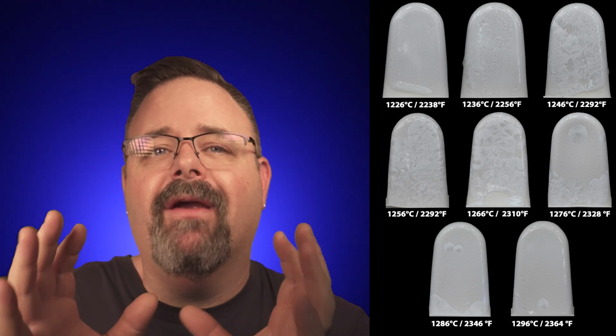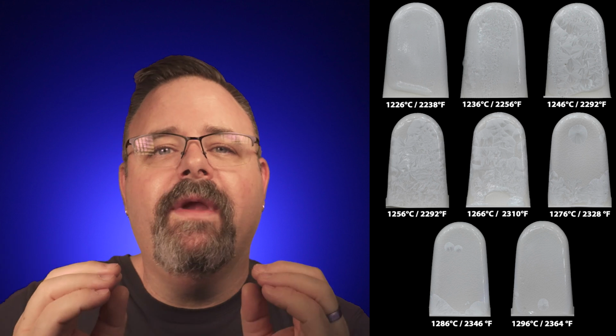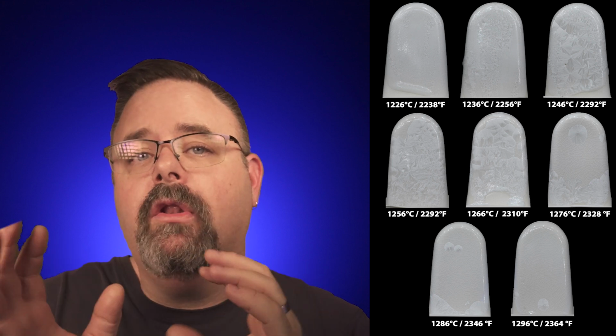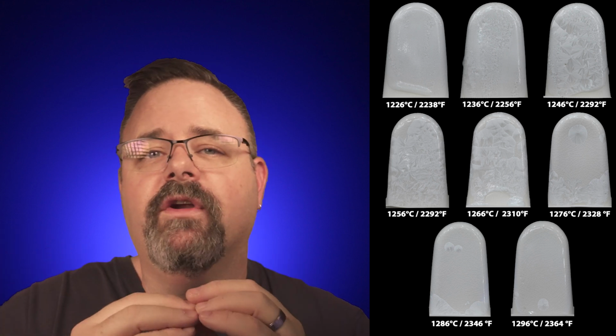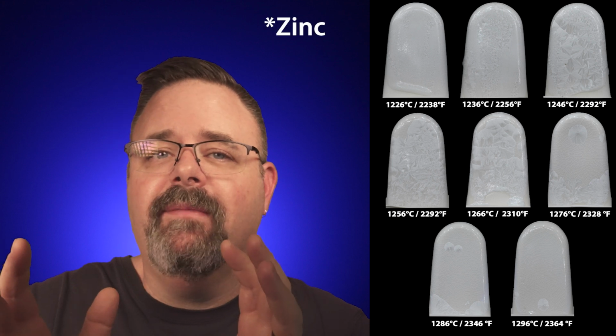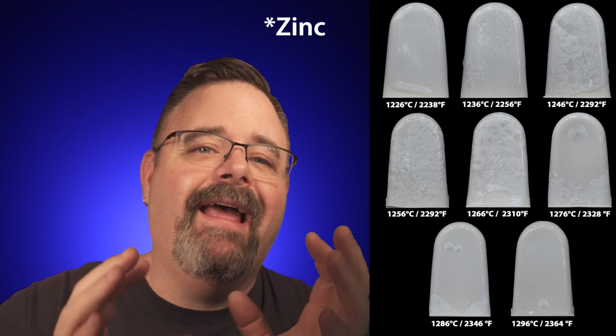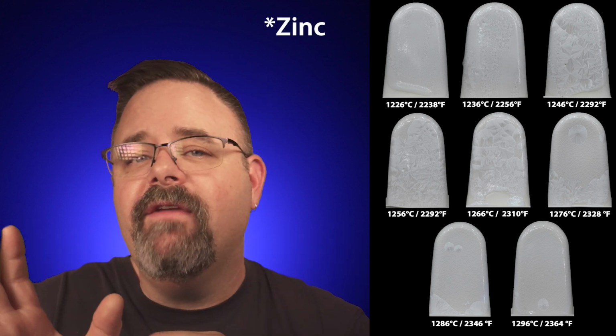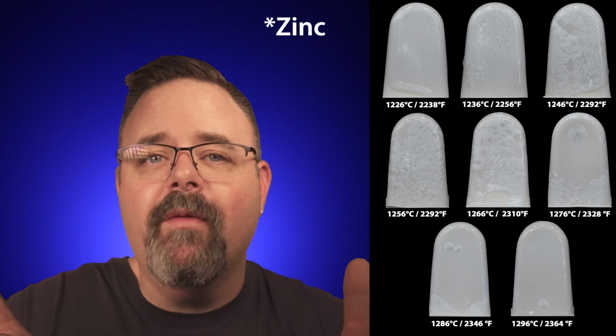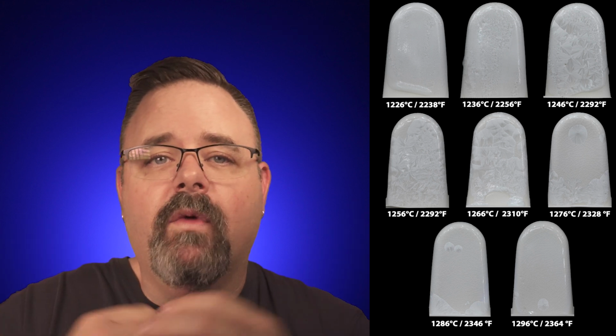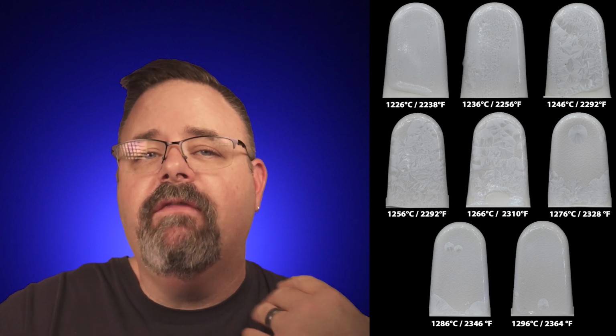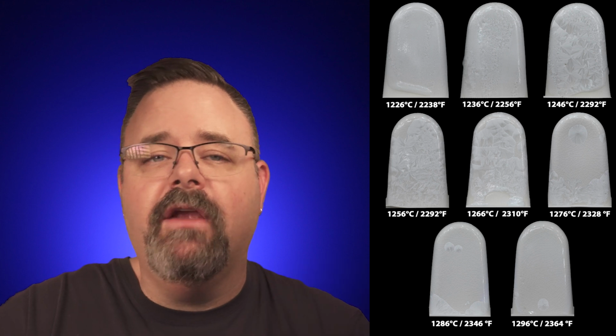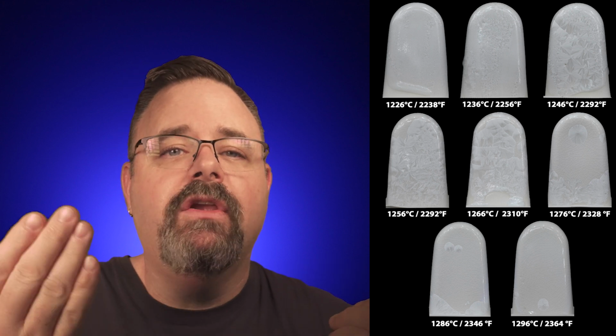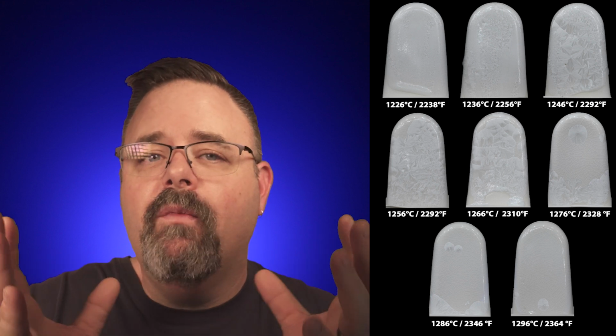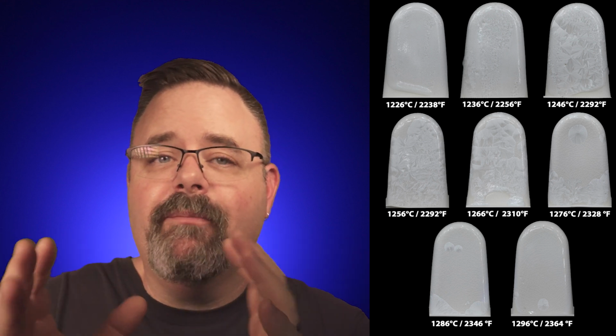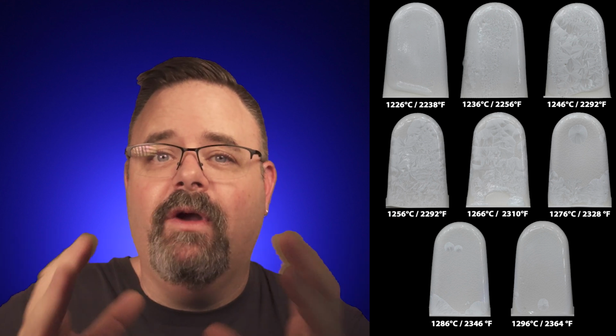But as we fire hotter and hotter and hotter, we see that we are getting fewer and larger crystals because we're dissolving more of that calcium into the glaze, so it's making less total crystals, until we fire so hot that we don't form any crystals at all. And this leads to one of my truisms about crystalline glazes. If you fire too cold, you're going to get too many crystals, and if you fire too hot, you're going to get too few crystals. And when you have a crystalline glaze, getting the perfect number of crystals is exactly what you're aiming for.